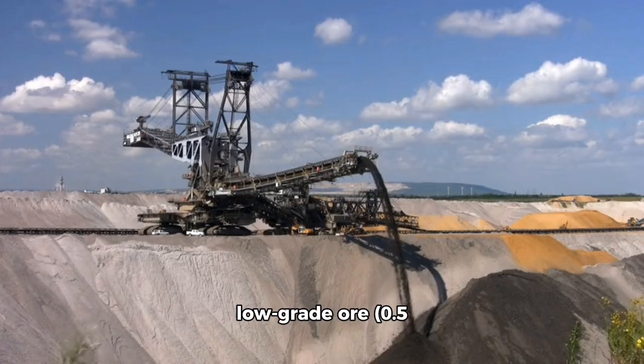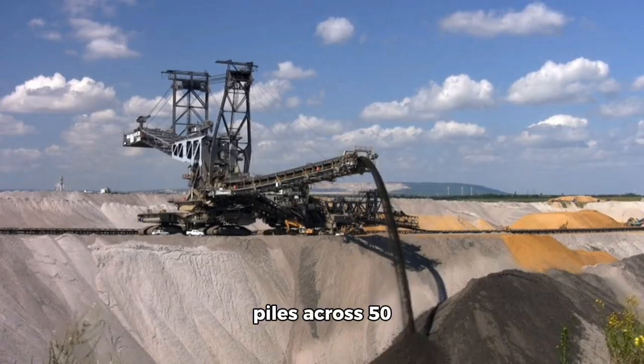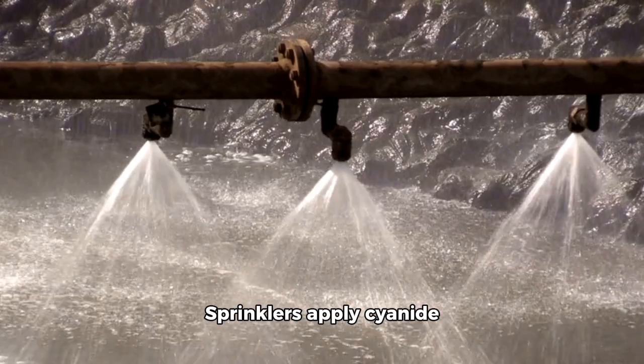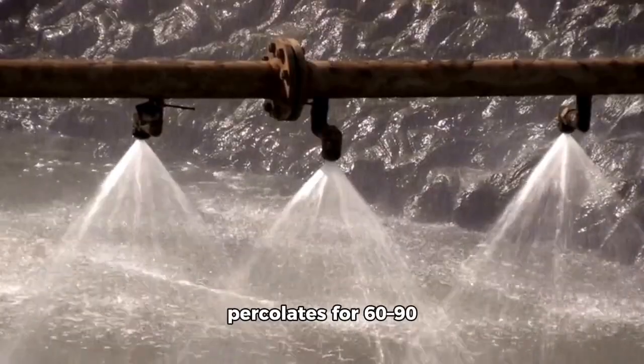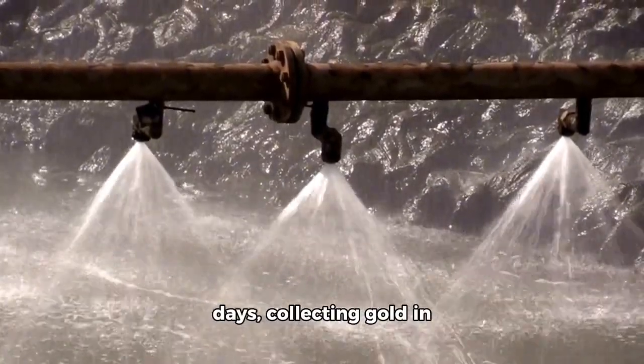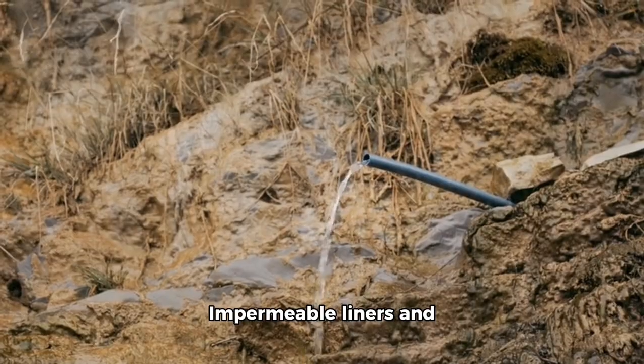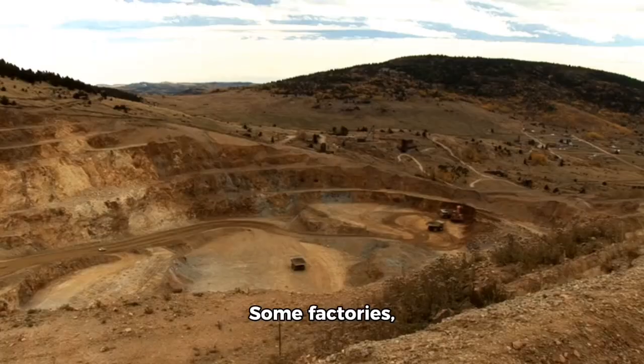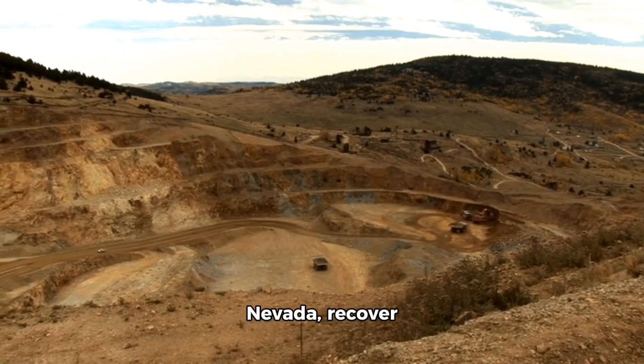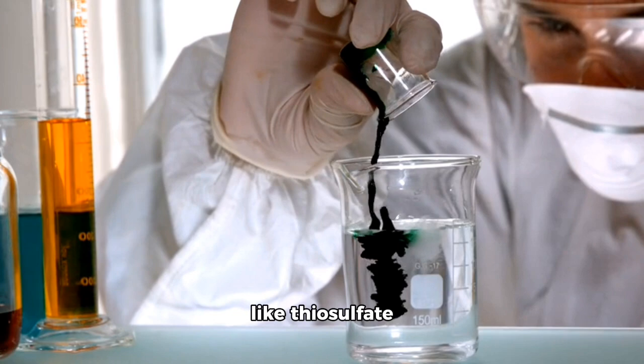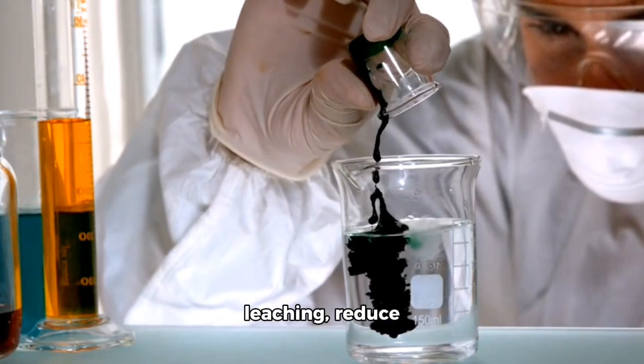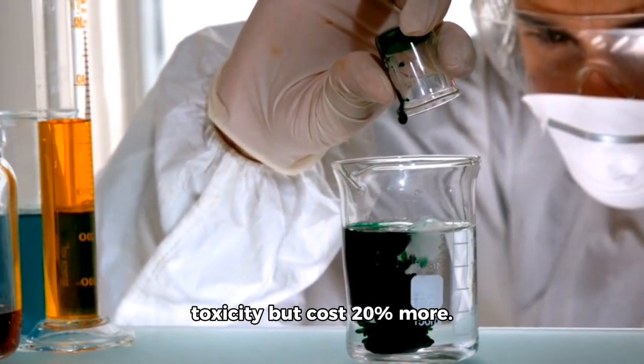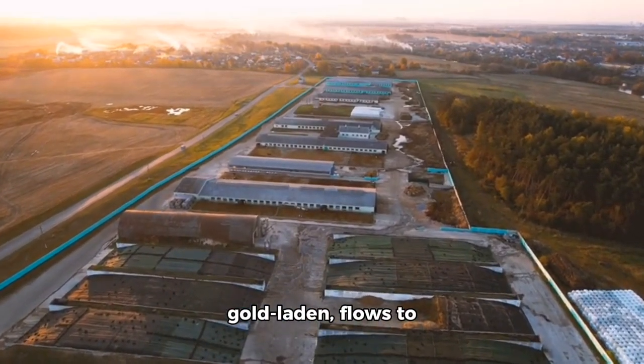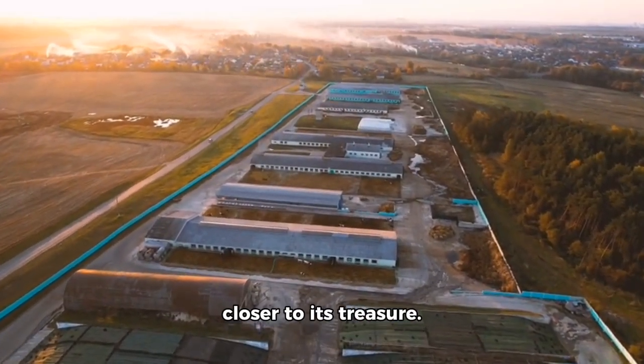Heap leaching, for low-grade ore of 0.5 grams per ton, involves stacking ore in 100-meter high piles across 50 hectares. Sprinklers apply cyanide solution, which percolates for 60 to 90 days, collecting gold in a pregnant solution. Impermeable liners and monitoring wells protect groundwater. Some factories, like those in Nevada, recover 70% of gold via heaps, recycling 75% of water. Green alternatives like thiosulfate leaching reduce toxicity but cost 20% more. The pregnant solution, gold-laden, flows to the next phase, carrying the factory closer to its treasure.